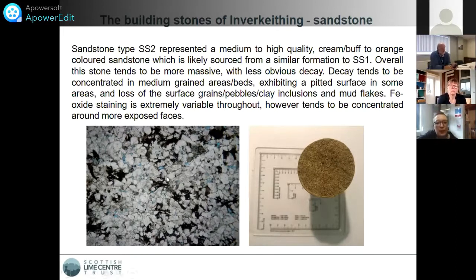But you can see that on the actual hand specimen, I'm not sure whether you can see in the picture, it's got a kind of speckled appearance. So it's pale brown and there are these darker browny orange speckles. It's these black iron oxides that impart that appearance to the rock. But you do see that there can be variations where in some parts of the stone this is not as obvious, and in other parts there's a lot more. And what happens in these regions is, as you can see, where all this black Fe oxides are, there is no pore space, because that is completely filled up, all that blue area and those pore spaces.